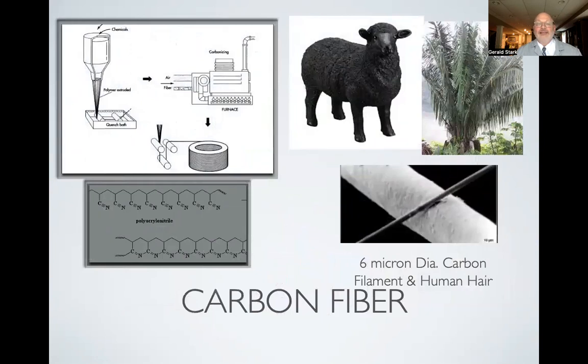So carbon, how is it made? Well, it doesn't come from carbon sheep. There's no carbon tree. It's really polyacrylonitrile, which is similar to a type of glue, acrylic glue, super glue, that's spun into a very small thread and baked repeatedly. And this is a typical carbon fiber that's about 6 microns, and that's the human hair right next to it. So these filaments are exceedingly small, and they're repeatedly baked, and the nitrogen bonds with the carbon are baked away. So all that's left is truly carbon.